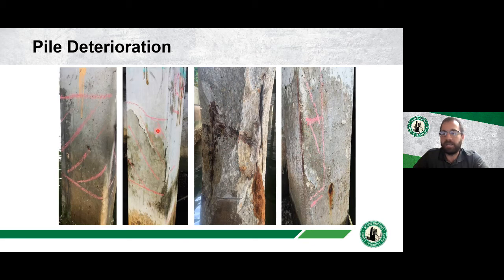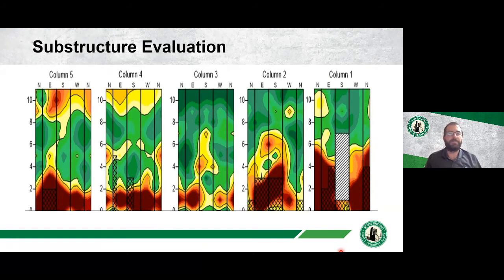So we were asked to take a look at this structure. You can see we've done some hammer sounding and identified delaminated concrete. Here, where we've chipped off concrete, we see clearly the rebar is corroded and broken. And so these piles are in need of corrosion mitigation.